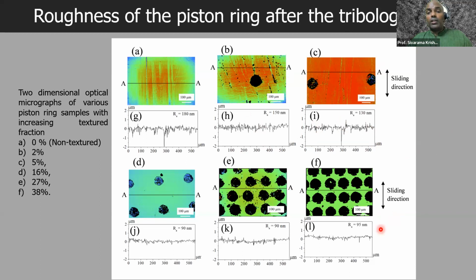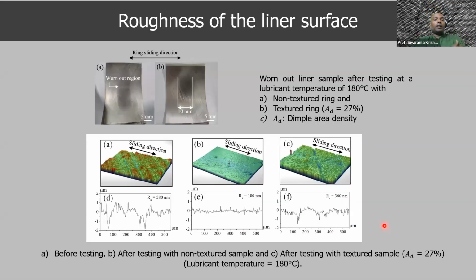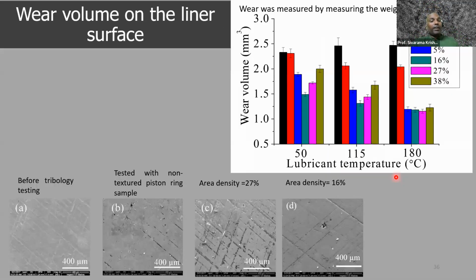We measured their roughness, their wear and tear, and indeed it's very clear that both the dimpled surface and also the liner, which I'm showcasing over here, were indeed much better with higher groove densities when we used femtosecond laser pulses to texture them. Okay, now the wear volume of the liner was also measured, but in the interest of time, perhaps I should not elaborate the details too much. We could maybe discuss this in our question answer sessions.